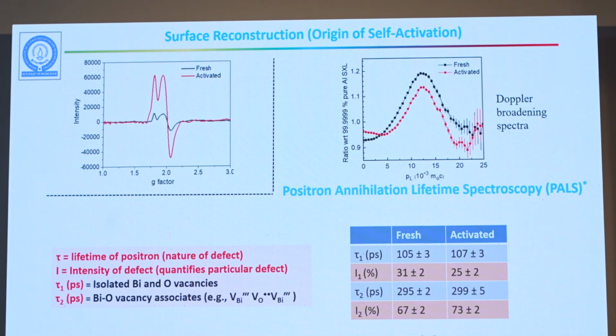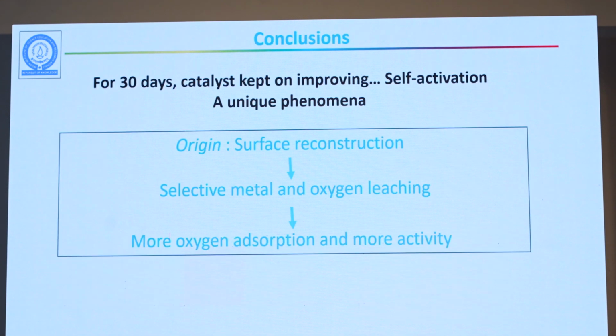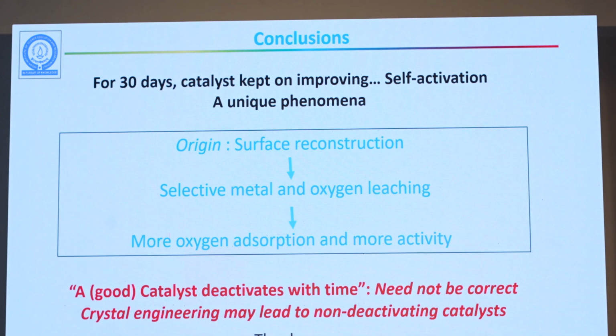Now, what we figured out is that as time passes, we had individual vacancies. They come together and form vacancy clusters. And these vacancy clusters are negatively charged. As a consequence, we have more and more oxygen vacancies on the surface. Oxygen comes and sits there because the oxygen vacancy was there. The metal was hungry, oxygen can sit there. Therefore, it gets converted to superoxide radical, and then it gets converted to H2O2. That is the origin of why we get more and more oxygen molecules.